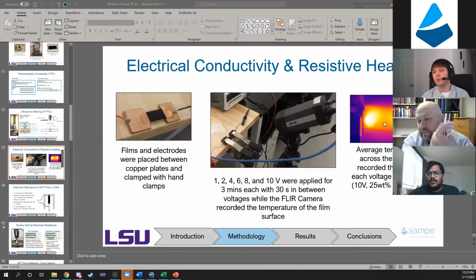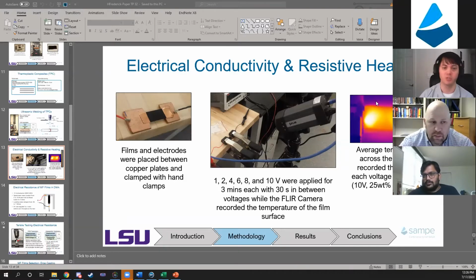Yes. That just has to do with the distribution of the nanotubes in the polymer film itself after being compression molded. This one in particular has 25 weight percent of the nanotubes. It has to do with how the network of nanotubes is arranged and how the electrons flow. So it's a result of the processing conditions, really. So would you want them to be better distributed throughout? Yeah, and this one shows they group up in these high temperature zones. So it just shows that they are not very well distributed in some of these samples. Okay.